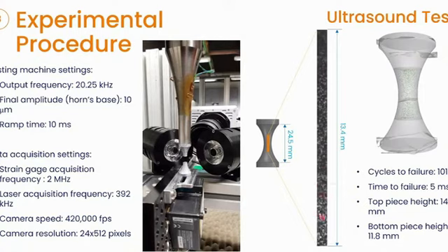In the recording, it's shown that the fracture in this specimen occurred a little below its center, which is also confirmed by measuring the scanned pieces after the second CT scan, showing that the top piece is indeed larger than the bottom one. This specimen in particular withstood 101 cycles until failure, and the time to failure was 5 milliseconds, which was not enough time for the machine to get to its final amplitude.